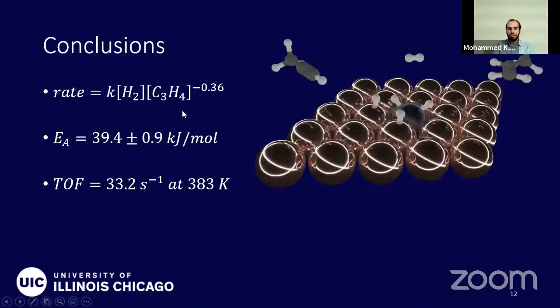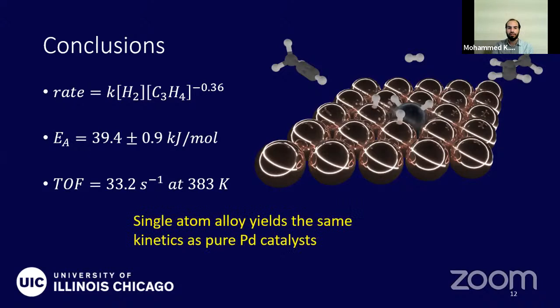So to conclude, we found that we can determine the rate equation for the hydrogenation of propyne over a single atom alloy surface, and that it has the same energy, it has the same kinetics as a pure palladium catalyst. So that basically tells us that using 2% of the material, we can get the same kinetics with the advantage of the selectivity of the copper here.